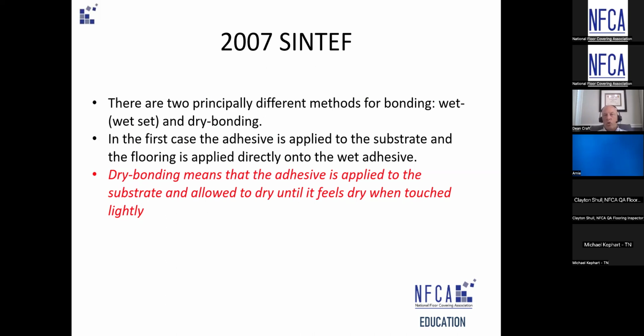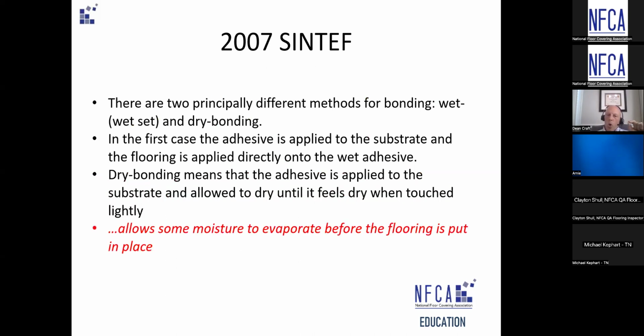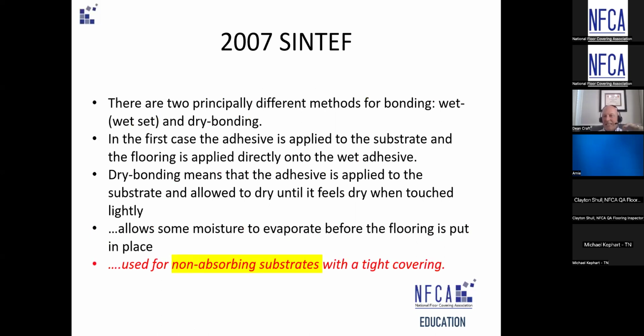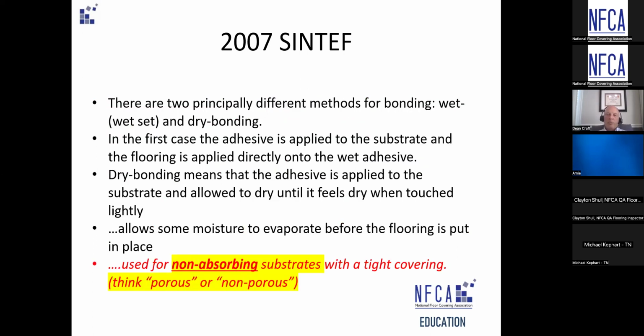Some are dry. Those are thinly applied, they're going to off-gas quickly and be dry to the touch. Your pressure sensitive adhesives are those kinds of adhesives, the ones that tack off quickly, put on with a paint roller. Those are good for that. But one of the things it really points out is these substrates. Be very careful, because how you apply your glue has an effect on what kind of substrate you need. And this was pointed out as far back as 2007. So the whole thing about absorptivity, they said non-absorbing. In the US, the words porous and non-porous were used, which were actually never correct.